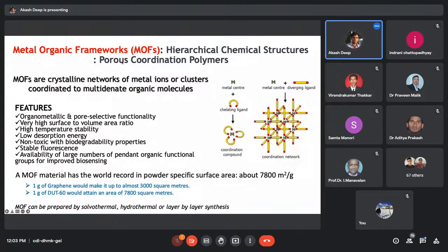So here you can see, when we talk about the difference between coordination compound and MOF, this simple figure explains the difference. Metal center plus chelating agent will lead to the formation of a coordination compound. But if we have a diverging ligand, then what we ultimately achieve is a framework which has pores in its structure, and this framework is repeated to form the polymers. These frameworks are the crystalline network of metal ions coordinated to multidentate organic molecules. So we have one metal ion and one multidentate organic molecule, and these are then forming a coordination complex.